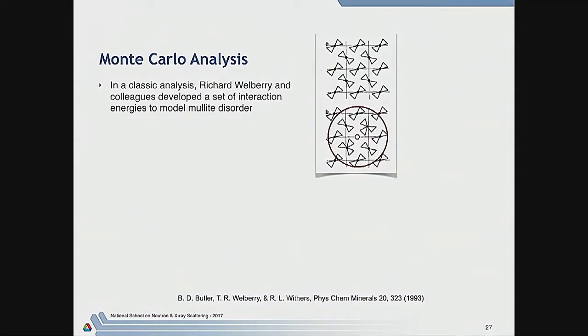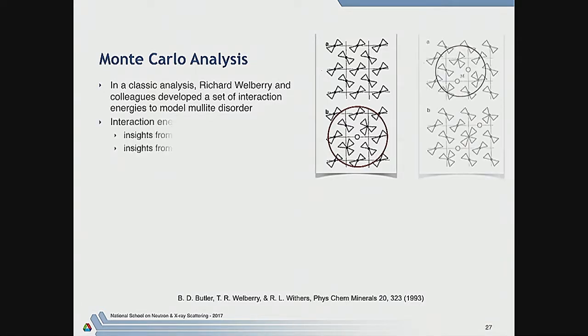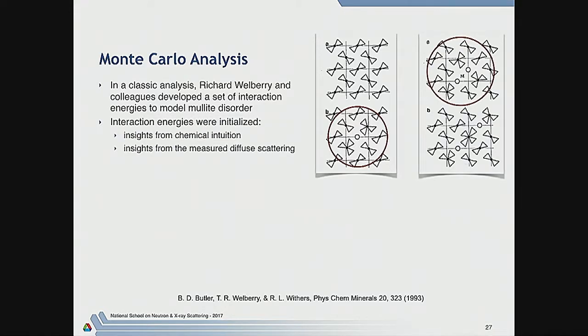And the way that we used to do this, or at least the way that very smart people like Richard Welberry used to do this, is they'd use a mix of chemical intuition with Monte Carlo optimization of the data. So for instance, they could work out that you're not going to get two vacancies together because there's nowhere for this central cation to move. And there are other things here where they're not even going to be here because this oxygen becomes way overbonded. All the cations around this vacancy move here, this one moves there, and you end up with 4 cations around this one oxygen.